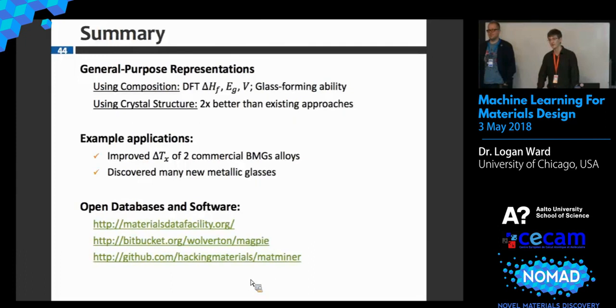So if you took out all the metals and only trained it on systems that really had a bandgap, have you tried? Does it improve? Yeah, effectively we tried something similar. Rather than directly train on bandgap, we first train a model that, given composition, will identify whether it's likely to be a metal or not, which we can achieve pretty strong accuracies for. And then given those two subsets, we train a machine learning model. It's been a while since I ran that exact test, but it was a significant improvement on the model's accuracy. So it's effectively doing that kind of approach with a data-driven method.